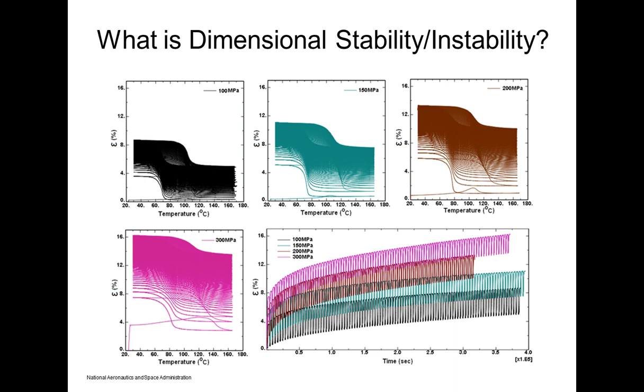Okay, I can do mechanical cycling faster than I can ever do thermal cycling. So if I have to reduce my levels of stress, I can drive the evolution mechanically to get to the desired state. Now, in any given case, what I'd really rather do is pick a temperature and isothermal stress path that allows me to do it with a single loading and unloading. But sometimes I can't get there depending on these material issues. So I use this construct both cyclically or, in the limit, a single loading and unloading to achieve that desired state.